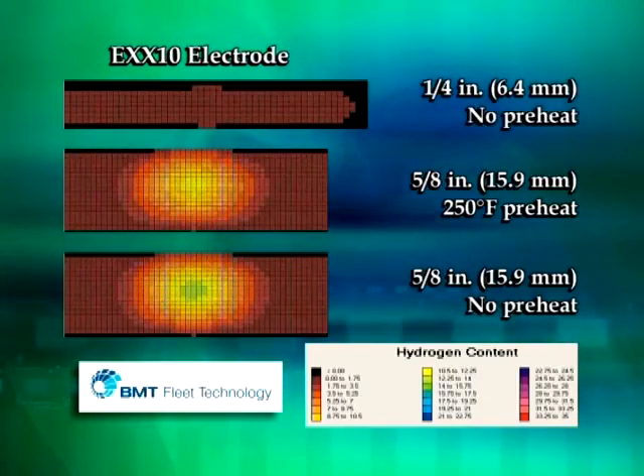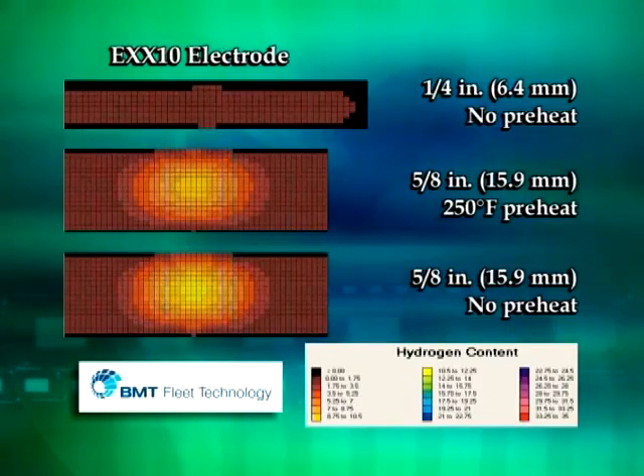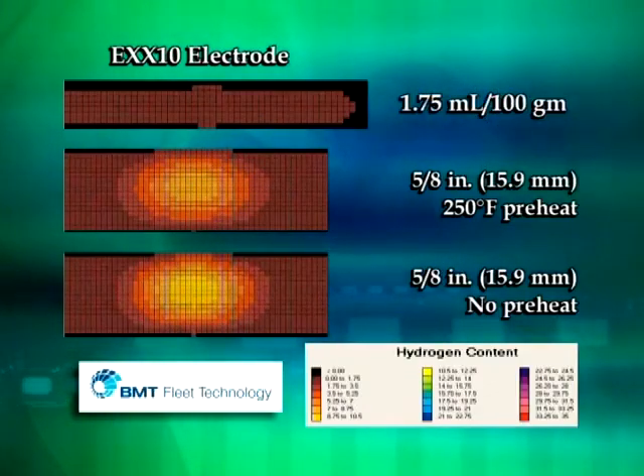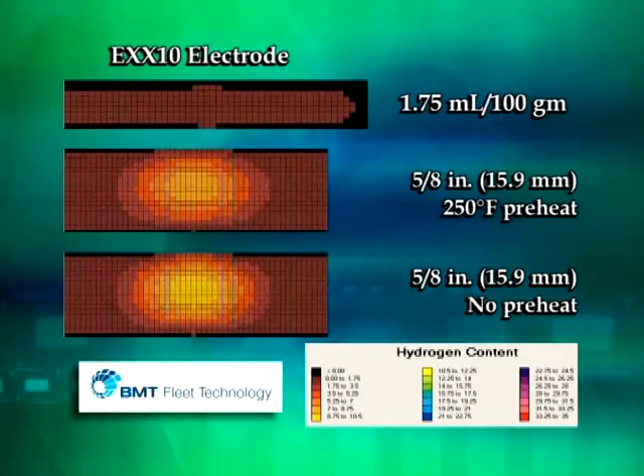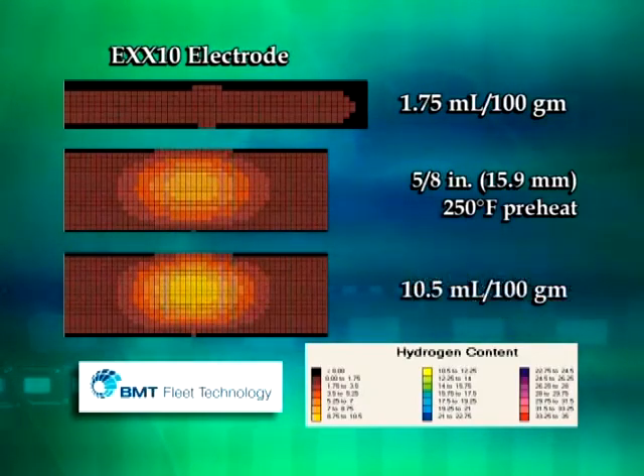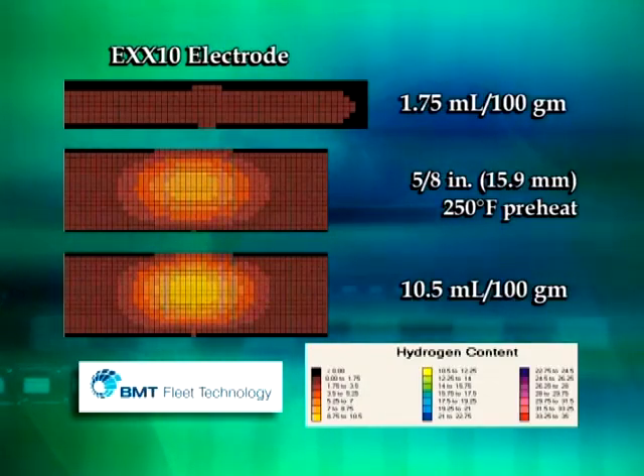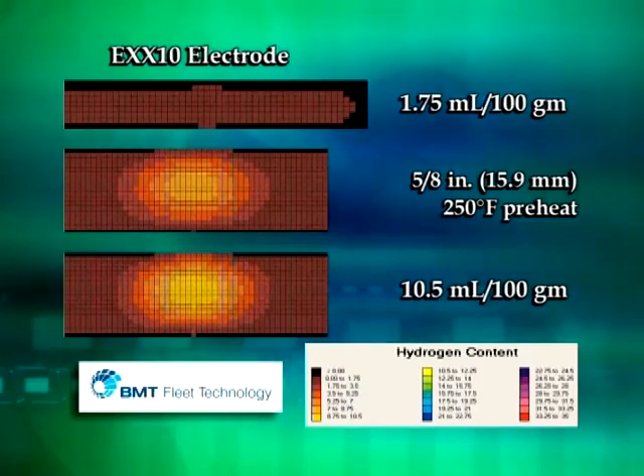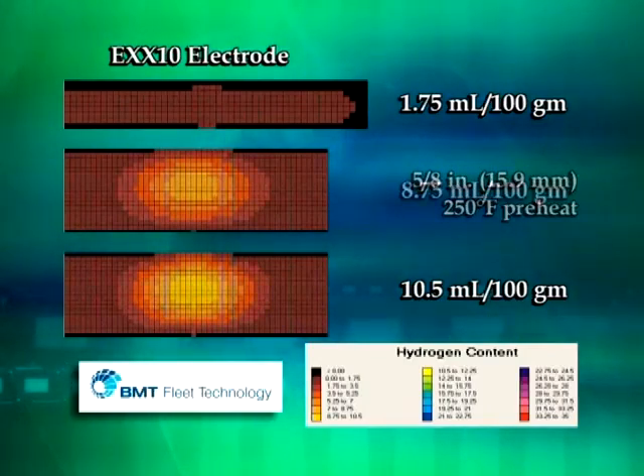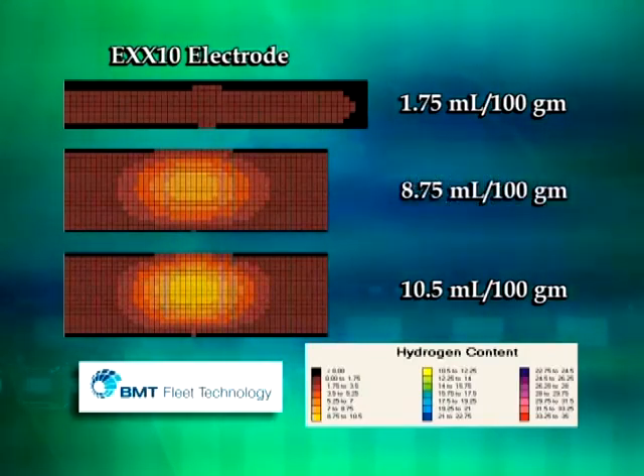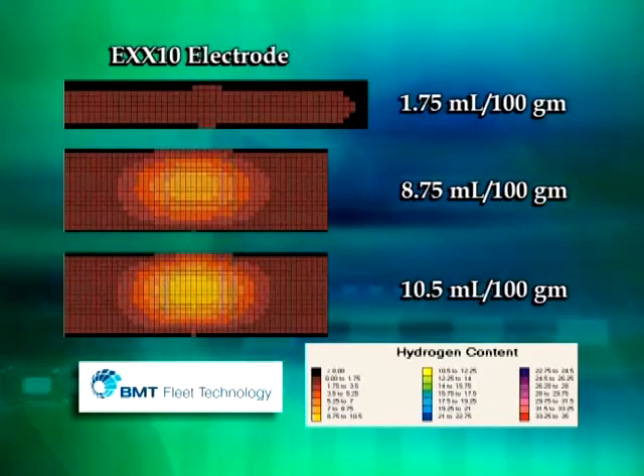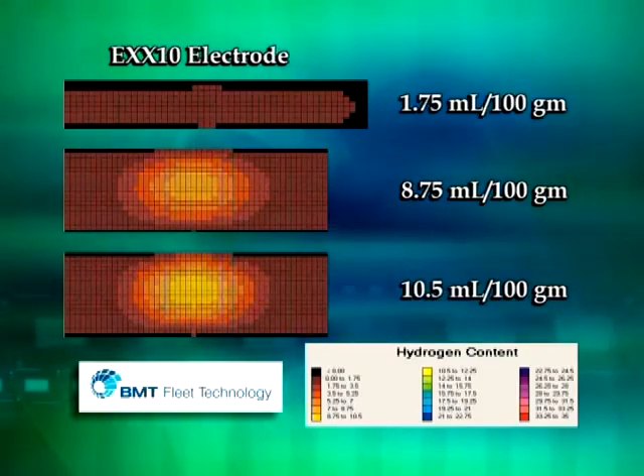The maximum hydrogen levels present 3 days after welding are 1.75 milliliters per 100 grams for the 1/4 inch thick pipe and 10.5 milliliters per 100 grams for the 5/8 inch thick pipe. The 250 degree preheat for the thick-walled pipe allowed more hydrogen to diffuse away and lowered the maximum remaining hydrogen level to 8.75 milliliters per 100 grams. Post-heating following the completion of welding can further reduce weld hydrogen levels.